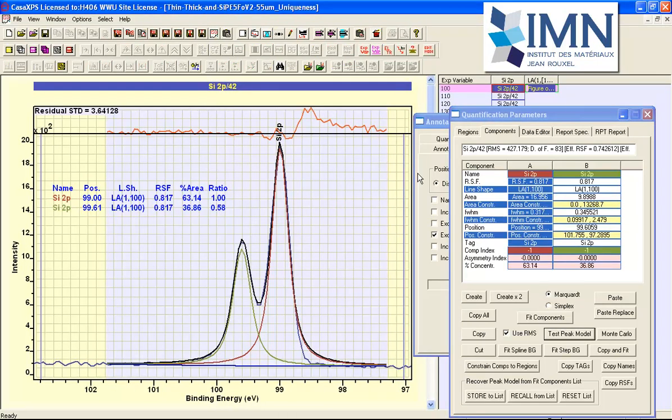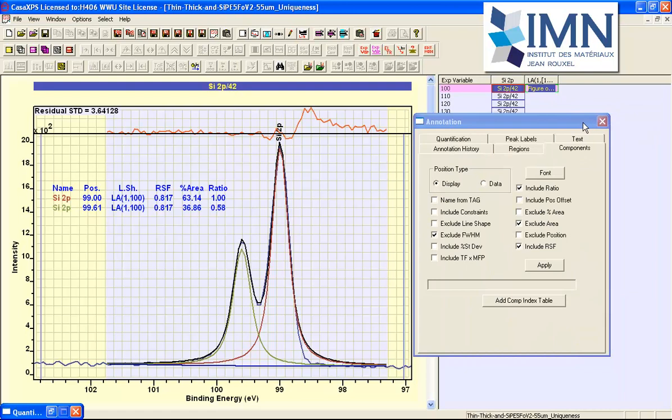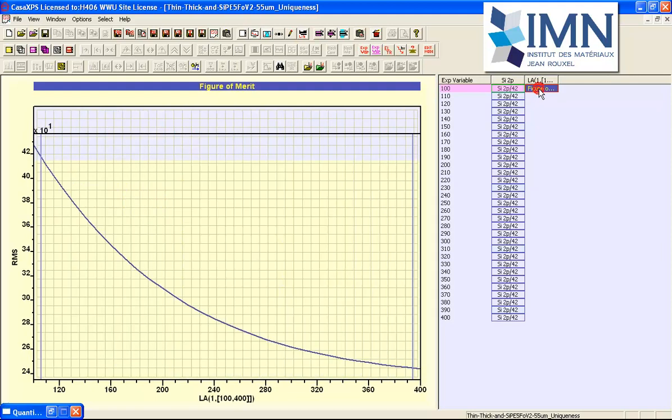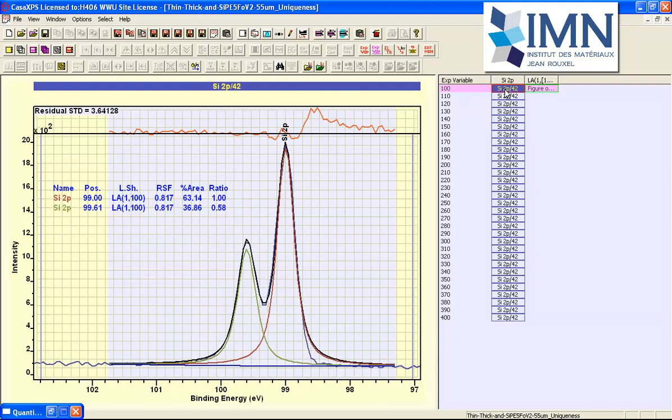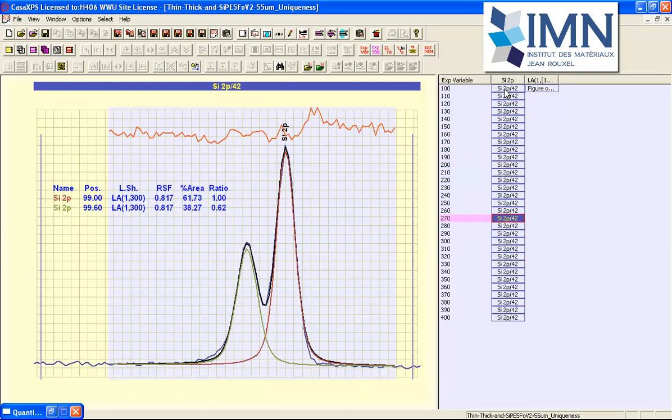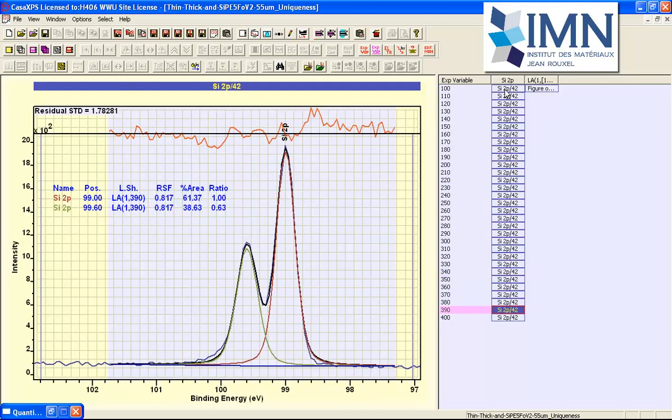And then after a period of time, a new file is created, and the new file contains a figure of merit plot, so we can see how the residual standard deviation or the RMS is changing as a function of that line shape parameter, and also the data has been copied multiple times and fitted using the different line shapes. So it started with 100 and then it's incrementing so that we can step through and see how the line shape parameter has altered the shape and the fit of these data with these two line shapes. So at this point you can see that